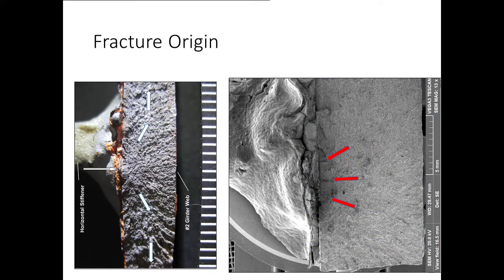So I took it to my failure analyst, and here's an optical picture. You can see here's the horizontal stiffener. There's the end of the fillet weld that's pretty gloppy. And here's the fracture surface in the web. And typically when you see chevron details like this, and there's some above that didn't show up here, they point back towards the source of the failure, which seems to be in this area in here, which meant the crack went this way, shown by the white arrows, and that way downward. So this was the area of concern.